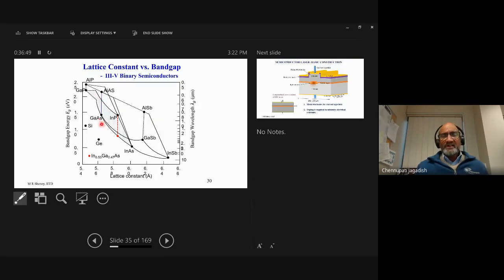I've already talked about a wide variety of semiconductors, and I was mentioning indium gallium arsenide earlier. By choosing this particular composition, you can achieve lattice matching of this structure, so that really plays an important role. And then you can choose what materials are appropriate. For example, gallium arsenide lattice constant is very close to germanium. So that's why these multi-junction solar cells are grown on germanium substrates. Silicon is lattice matched to gallium phosphide, and people use gallium phosphide as a buffer and then gradually change the composition, thereby minimizing the dislocation formation and other things.